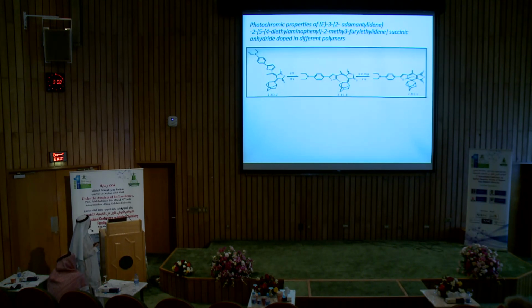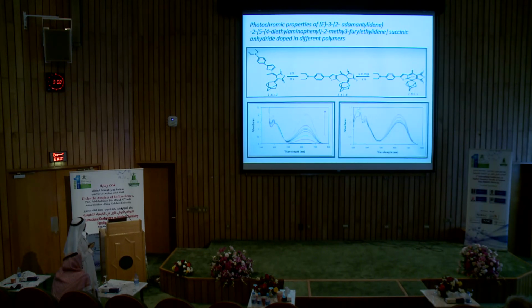We studied another fulgide, which is this amine derivative. This compound, because of the long conjugation, is colored from yellow to deep red, deep blue, or deep green according to the alkyl group pendant on the left-hand side. So you can see that we shifted the maximum absorption of the closed form to about 600 nanometers. And of course, these kinds of compounds, because they are shifted further toward the far end of the visible region and maybe the near infrared region, have some application in optical data storage at the time when we prepared such compounds. And this compound can find good applications in optical data storage using a laser that emits light in that region.